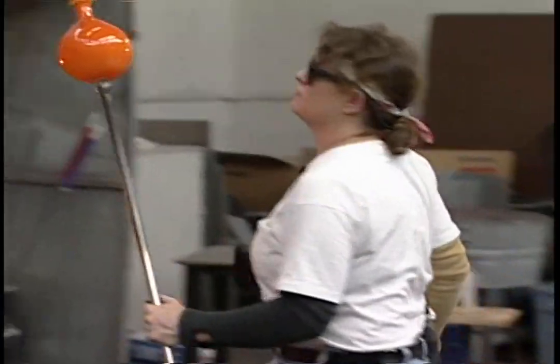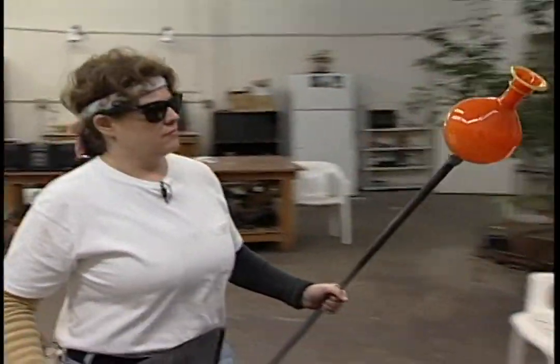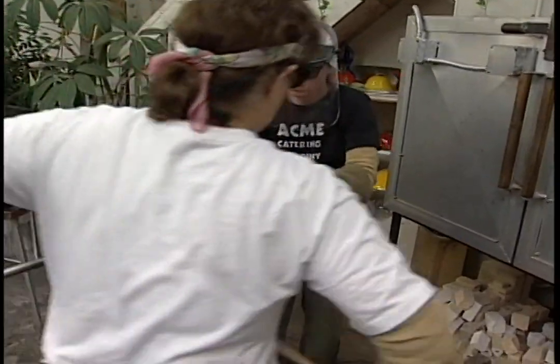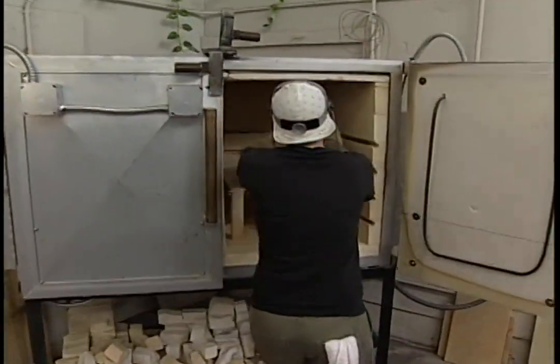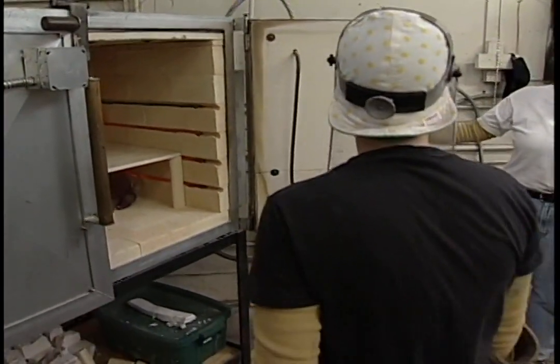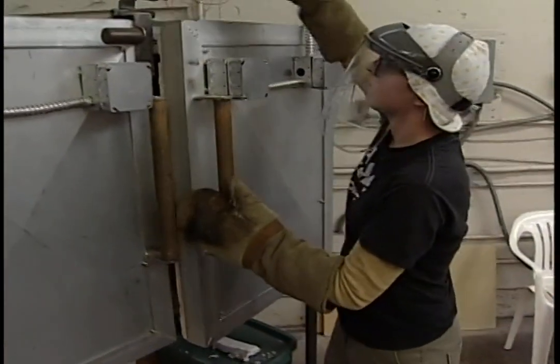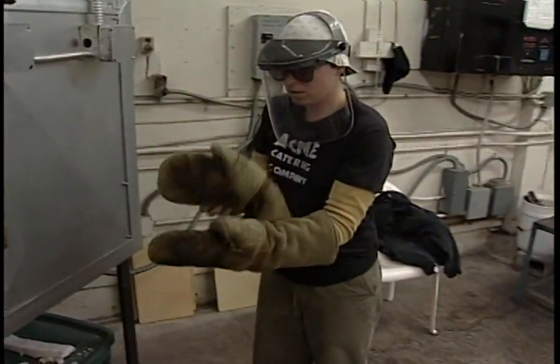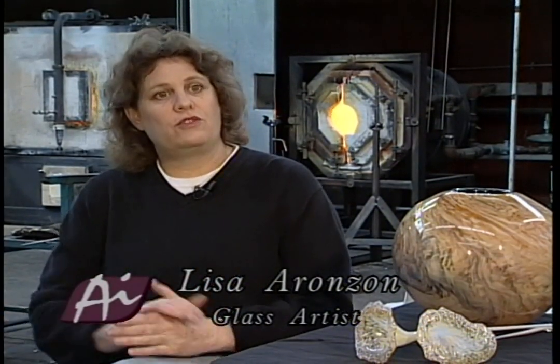It has to have 12 hours to cool in an electric oven called the annealer. Annealing means to cool slowly. So all day long we blow pieces, put them away in what's affectionately called the box, or the annealer, and that's controlled by a computer. The temperature is kept around 900 to 1,000 degrees. And then at night it's cycled down to room temperature through various stages of cooling to relieve stresses out of the glass. Otherwise it breaks. It just can't take the stress of going from 1,000 to room temperature in a few minutes.